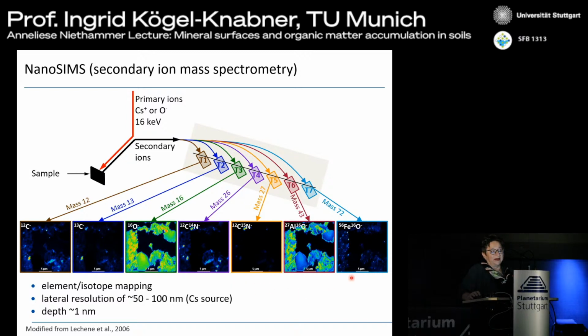These secondary ions are then separated according to mass. What we finally get, if we do this very often in a scale of, I think it's difficult to see, this is 5 microns, so totally it's 25 by 25, or 30 by 30 micrometers for a lot of what I will show. And what we can get is at the same time a distribution of elements, but also of isotopes. So we can take advantage of the fact that we can separate the C12 mass from the C13 mass and can use labeled materials that we add to the soil and that decompose in the soil, and we can trace the organic matter that comes in. And I will show an example for that.